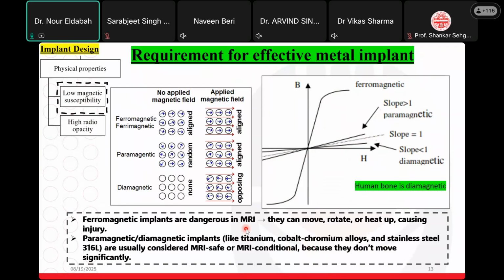Also, the magnetocaloric effect. The magnetocaloric effect means that when a magnetic field is applied to a ferromagnetic material, it will heat up the implant. Considering that our body temperature is around 37 degrees Celsius, heating up the temperature to 50 or 60 degrees Celsius will harm the tissue surrounding the implant and cause loss of the implant in some cases. Also, the thermal expansion coefficient of the metal is not like that of the human bone, and in this case it will press on the human bone, causing severe pain from the implant.